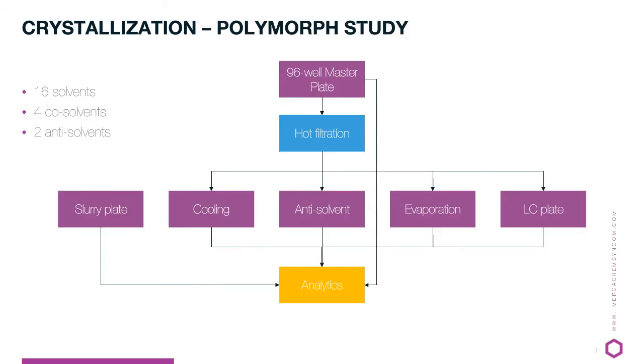Here is a simple example of a polymorph study. You can find these in literature. These are different methods, and it's actually one scheme that fits all issues. You have different methods available: cooling crystallization, anti-solvent addition, evaporative crystallization. Use a slurry plate for recrystallization, an LC plate for determining how much is still in solution, or do we have decomposition. This looks very simple, and it's a nice base to start from, but it is not reality.